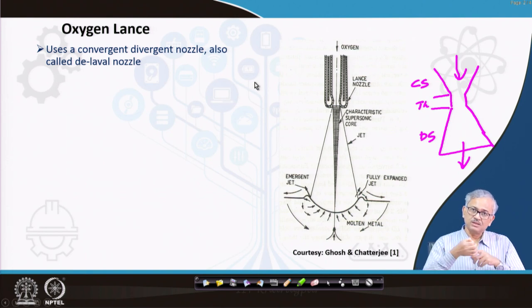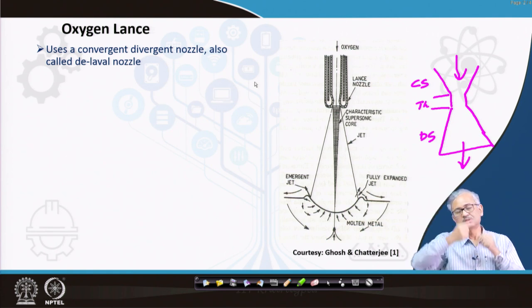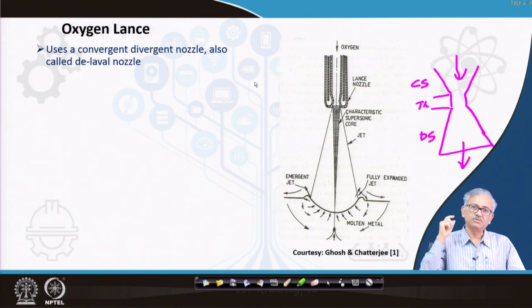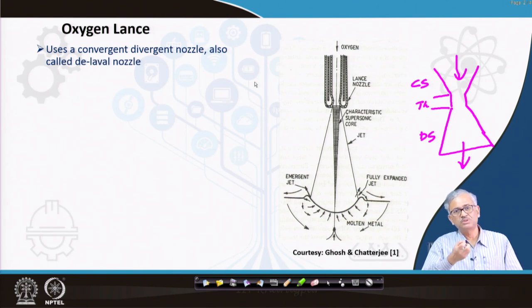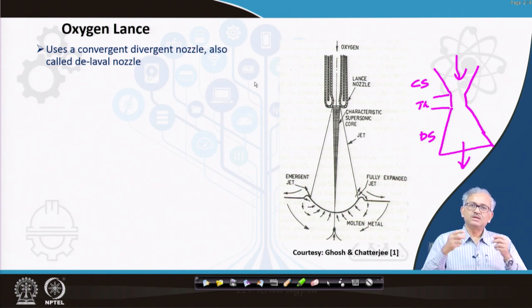But if I use a cylindrical nozzle, then I cannot push the oxygen at a very high velocity. What happens in the case of a cylindrical nozzle is that if you push the gas, you have to give a very high pressure at the upstream point, and when the gas comes out, it also comes out at a very high pressure. So from a cylindrical nozzle, the gas is expected to come out with a very large pressure. This high pressure oxygen jet then interacts with the one atmosphere ambient air, right? And as a result, most of the energy gets dissipated in the form of shock waves in the case of the cylindrical nozzle.